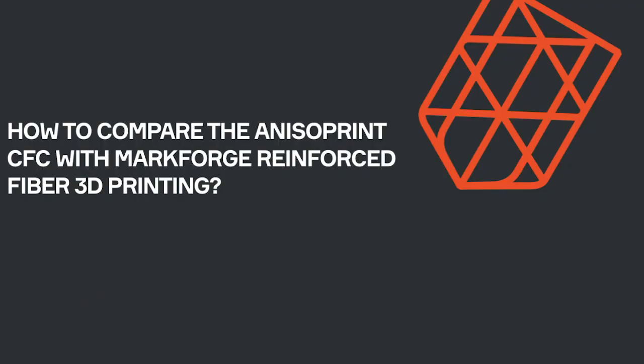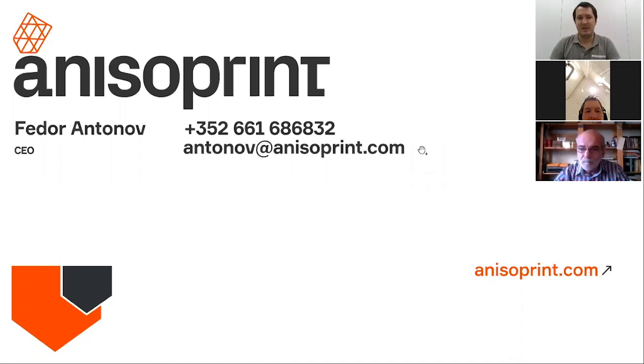How to compare the Anisoprint CFC with Markforged fiber 3D printing? It's simple. Markforged is prepreg based. Markforged pre-impregnates dry fibers, either carbon, Kevlar, or glass, with nylon, with a fiber volume fraction of about 28%, and then it's just simple material deposition where they melt the plastic inside the fiber tow and then place it.